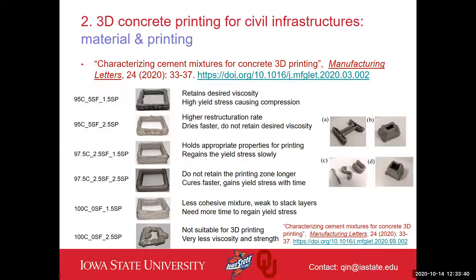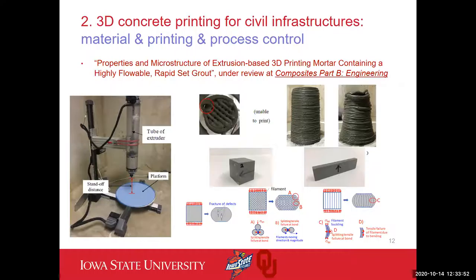So these are good structures. We continued using the best material combination that we found from those studies, and continued by directly printing not hollow structures anymore, but solid structures. Eventually the concrete material is mainly used for supporting different infrastructures, so they have to be solid inside. But 3D printing is printing filament by filament, layer by layer. What we want to see is whether the internal structure is good enough to support future mechanical testing. So we started to use the printer that you are seeing over here to print the filament structures, and then tried to identify how many voids are inside, and what the compressive behavior and the tensile behavior of the results are. This work is still under review, so I will not get into details.